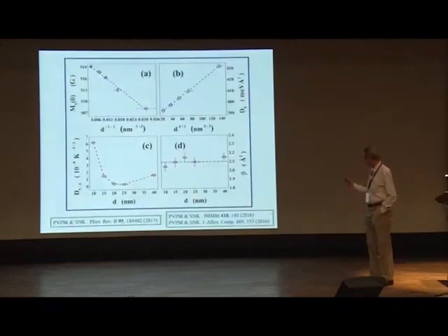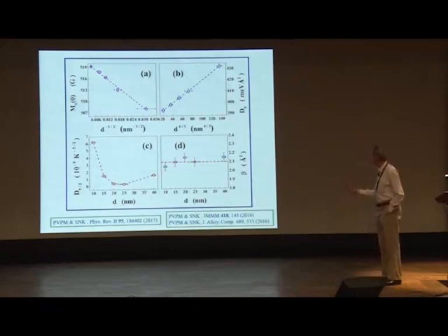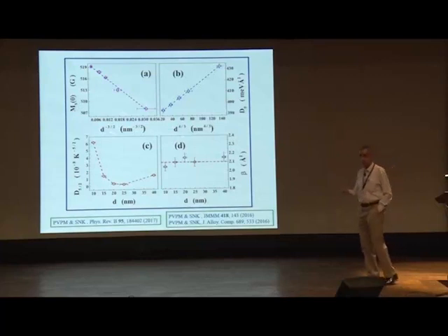And you see now these are the fit parameters as a function of thickness. You see that the spontaneous magnetization at absolute zero and spin wave stiffness at absolute zero scale with the average crystallite size according to these power laws. So that would tell you that this average crystallite size is a relevant scale for spontaneous magnetization in these systems.